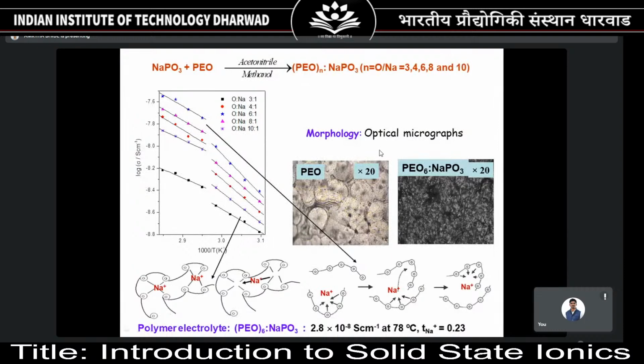So what has happened on addition of salt in the polymer? This is a polymer, which is semi-crystalline. You can see well defined spherulites, and when you added salt in it, you could see that the spherulite sizes have decreased, and you can see the amorphous content has increased.